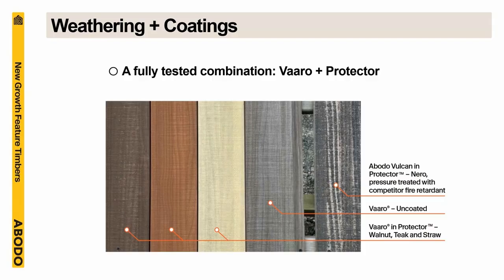So coatings are notoriously difficult to apply to many fire-treated timber products. So we wanted to be sure that we had a fully tested combination of our coating with the base material. And so here's a test. You can see there's a photo here and it shows the Vaaro on the left. The first 3 boards are protector coated boards with our semi-transparent wood stain, and then the 4th board is left uncoated, and this is weathered for 18 months.